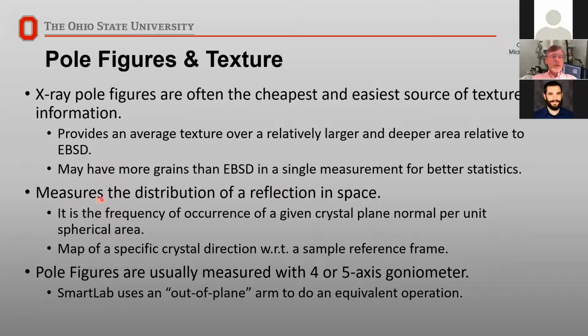So what a pole figure does is it measures the distribution of a particular reflection in space. Remember that a reflection here is indicative of a particular crystal plane. So it's basically telling us the orientation of that crystal plane around in space. Which way is it pointing? You normally describe that with respect to some sort of a sample reference frame. And because this has come out so often in metallurgy, it's often referred to as the rolling direction and the transverse direction. Normally now, people will use a 4 or 5 axis goniometer to measure these things. And there are some pluses and minuses to this. On our SmartLab we don't actually have one of these goniometers. However, we do have an out-of-plane arm, and we can do something equivalent to the 4 or 5 axis goniometer. And I think there are actually some advantages to using this out-of-plane arm.